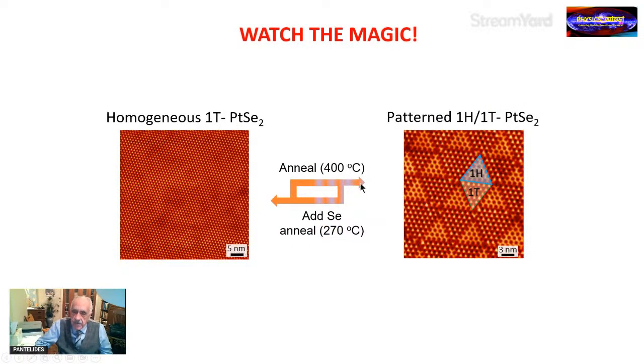Additional experiments showed that if you anneal it at 400 degrees Celsius, very carefully, and it took a while to figure out how to get perfect triangles, you get two different triangle structures of two different arrangements of the atoms in the material, the 1H and the 1T structure. Then if you go back and lower the temperature, you can recover the original one, but you have to add selenium. So it was evident that these triangles are formed by having selenium vacancies, and we demonstrated with theory that if you have a lot of selenium vacancies, they pattern out like that and give you the triangles.